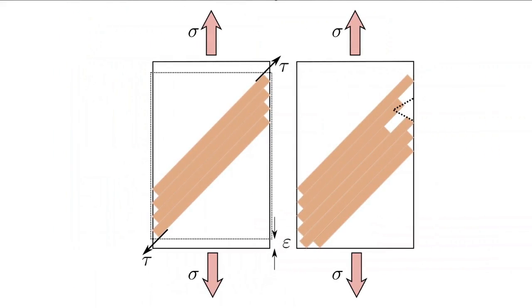If you recall the lecture on plasticity, I described that slip occurs on favorably oriented slip planes. In a polycrystalline material, some grains have their orientation such that slip is achievable once the yield stress is achieved. However, as we know, there are many grains that make up a metal, and there can be a grain or several grains that have their orientations such that slip can occur below the overall yield stress of the material. Cyclic loading will cause this slip to localize and start to create a flaw-like feature on the surface.